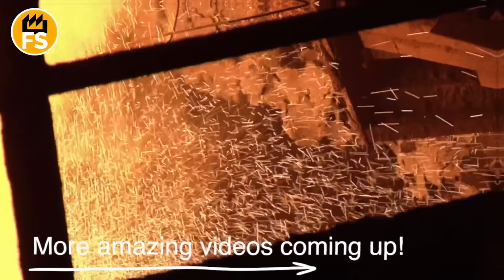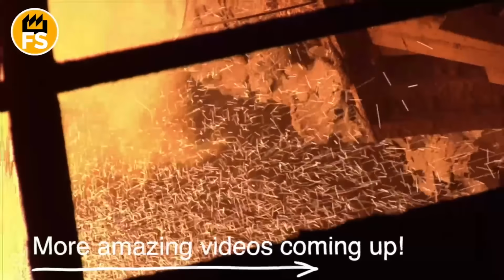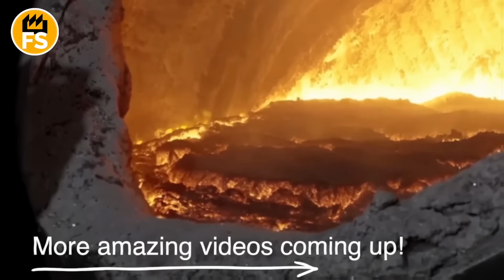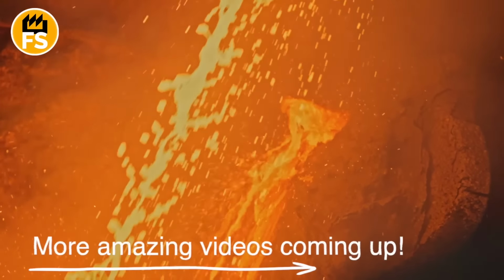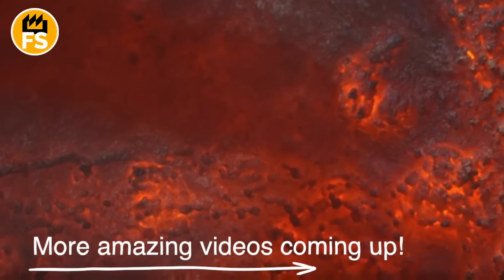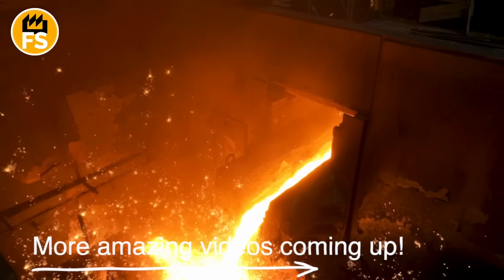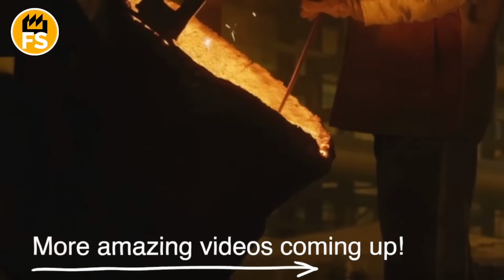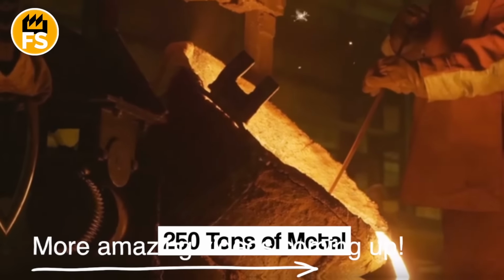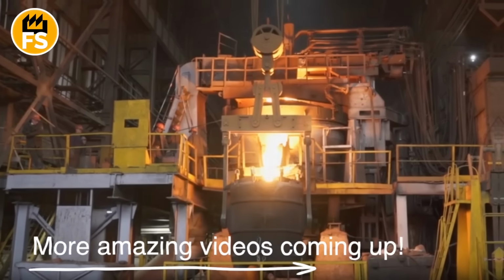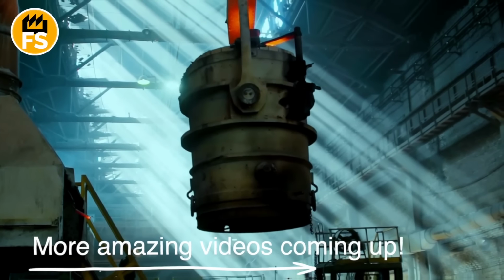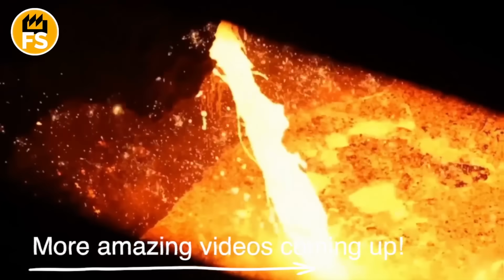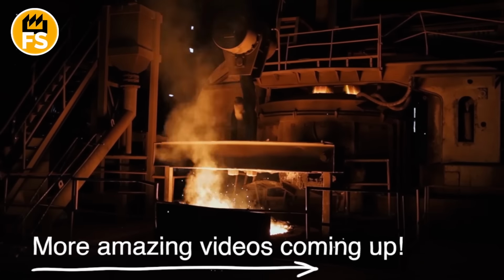What's happening inside is that the extreme heat is literally ripping iron atoms away from the oxygen and other elements they're bonded to in the ore, and all the waste material rises to the top as liquid slag that gets poured off and ends up being used for cement production. The pure molten iron sinks to the bottom and collects in this glowing orange pool that you can see through special observation windows. And every few hours, they tap the furnace and the liquid iron flows out into these enormous ladles that each hold about 250 tons of metal. Those ladles get picked up by overhead cranes and moved about 60 feet over to the next building, where the iron gets converted into the specific type of steel needed for structural beams.